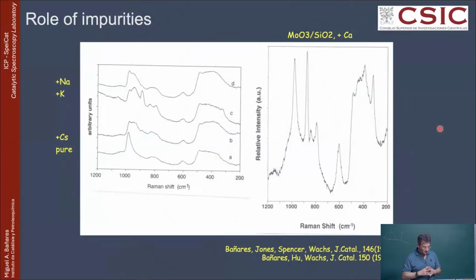Now, the other question, impurities. What happens with impurities or with additives, sodium, potassium, calcium? When you disperse molybdenum oxide on silica, this is what you get. Here you have a catalyst, which is molybdenum oxide on silica, and dehydrated. So this 1000 is the Mo=O, this oxo group of the supported molybdenum oxide. And that will be about 1000 more or less. So this is what you see here.